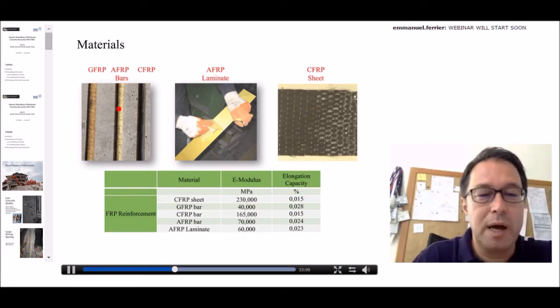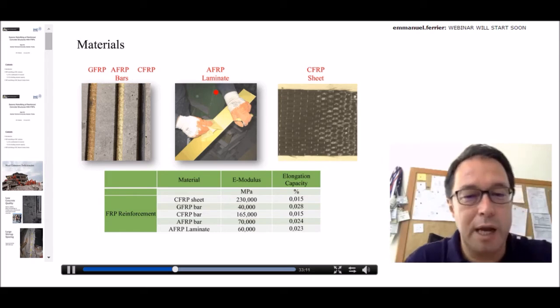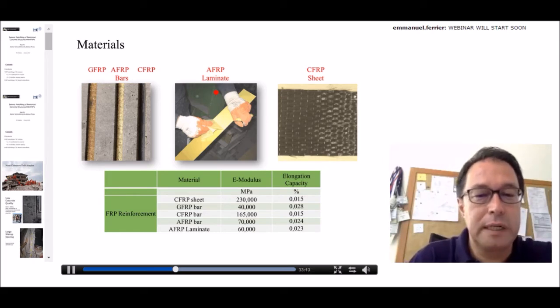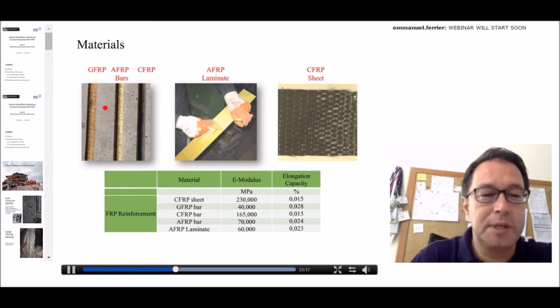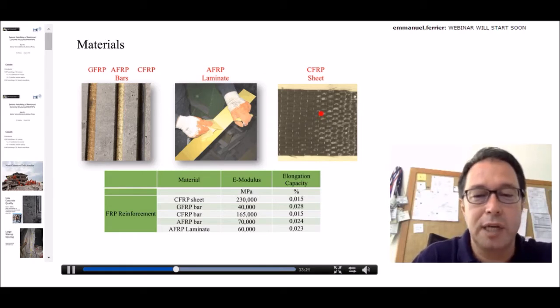Because when you apply longitudinal FRP bars or laminates, your flexural capacity increases, which could cause shear failure, which of course you never would like to have. Therefore, considering the capacity design principles, we increase the flexural capacity using any sort of technique. We should also take care of shear strength by, for example, jacketing with CFRP sheets in the transverse direction.